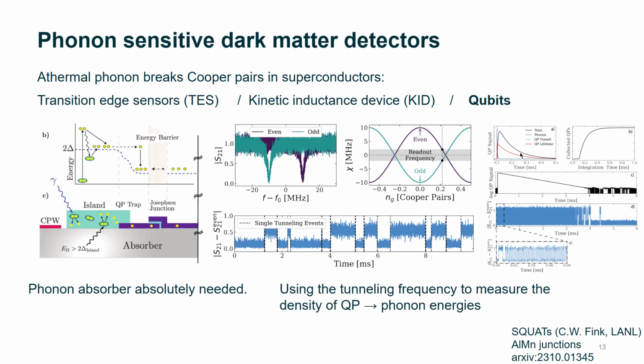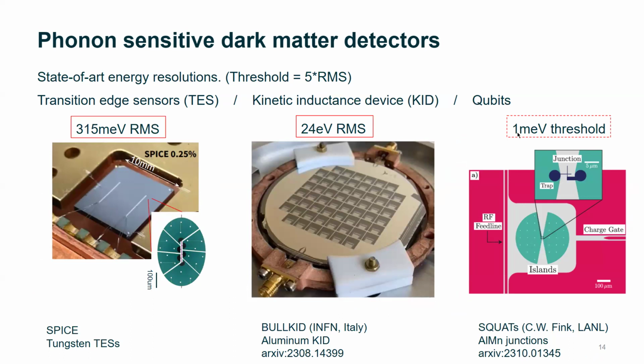And here they simulate a quasi-particle pulse. This is a time domain trace, and you start with a huge amount of fast jumping and it slows down. So we are looking for this feature. You can look for this feature on the baseline and use it to look for dark matter. This is a really nice picture, and with it, you can really achieve a 1 meV threshold. Basically, this is only limited by the superconducting band gap, which can go much lower than this as well.